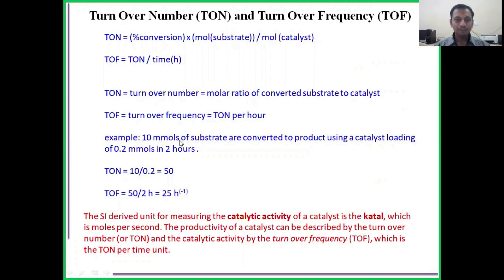So for example, 10 millimoles of substrate are converted to product using a catalyst loading of 0.2 millimoles in 2 hours. So the turnover number is 10 divided by the catalyst loading of 0.2, which is equal to 50. Turnover frequency is the 50 divided by the reaction time of 2 hours, so you get the turnover frequency of 25 per hour. We have to remember the SI unit for measuring the catalytic activity of a catalyst is the katal, which is moles per second.